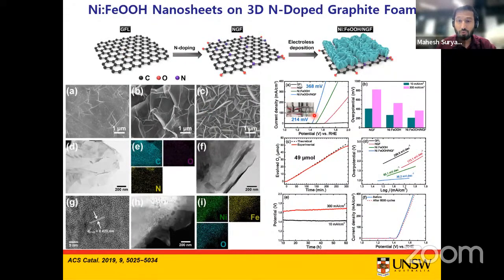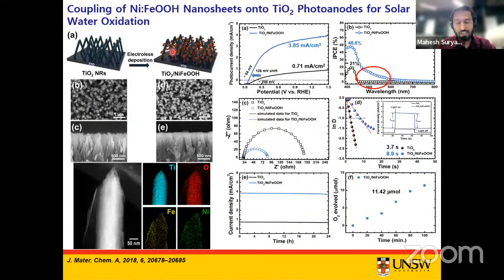That means the onset potential value is drastically reduced thanks to the nickel doping, which modulates the electronic structure of the iron oxide hydroxide. And this highly conducting nickel nitrogen doped graphite foam also helps to improve the electrical conductivity. And that again improves the performance. So based on these initial electrochemical measurements, we loaded this nickel based iron oxide hydroxide catalyst on